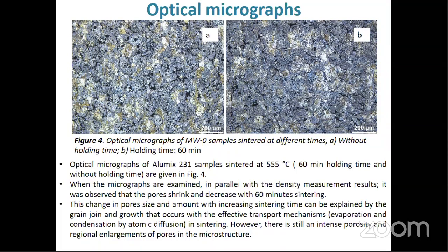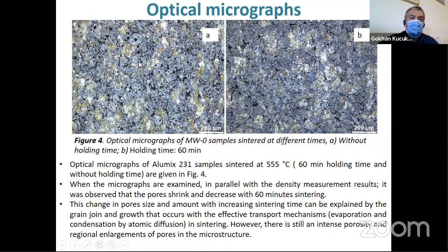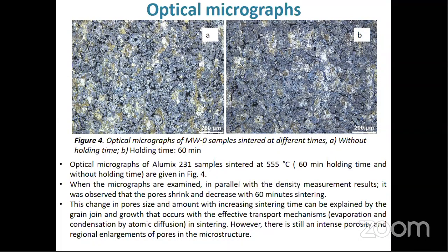Micrographs of Alumix 231 samples sintered at 555 degrees are given in figure 4. When the micrographs are examined in parallel with the density measurement results, it was observed that the pores shrink and decrease with 60 minutes sintering. This change in pore size and amount with increasing sintering time can be explained by the grain joining and growth that occurs with the effective transport mechanism in sintering. However, there is still intense porosity and regional enlargement of pores in the microstructure.